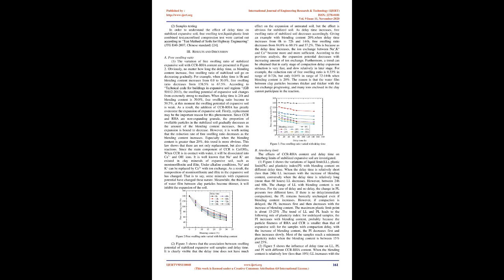At first, CCR and RHA are mixed with the optimum mixing ratio. Then, CCR/RHA are blended with expansive soil and the blending content is 0%, 5%, 10%, 15%, 20%, 25%, 30% respectively. After a while, the mixtures are stirred with water and stored in sealed bags for 0, 12, 24, 36, 48, 60, 72 and 144 hours. Until the certain delay time, samples are manufactured according to requirements of free swelling ratio, Atterberg limit, and unconfined compression strength test. In addition, part of the samples will be cured at 20 degrees Celsius and 95% humidity until 28 days for unconfined compression strength testing.